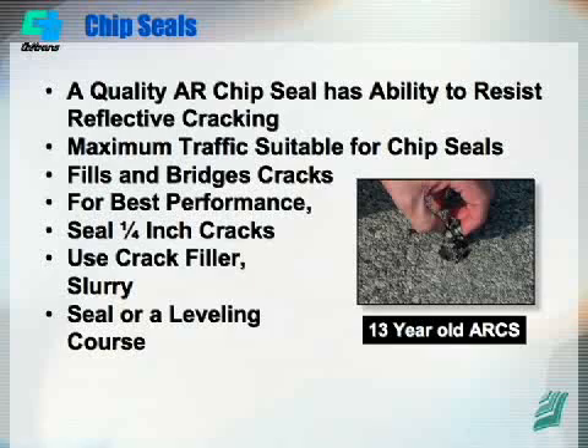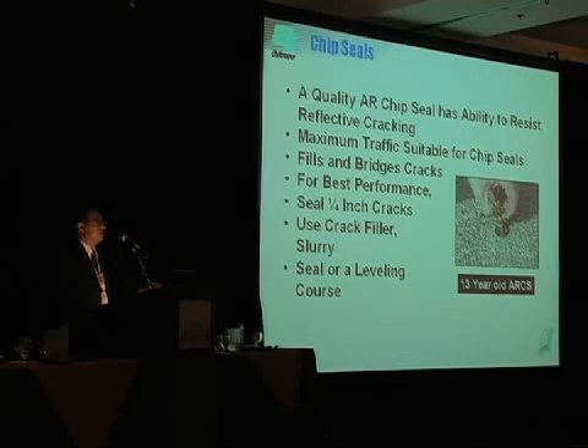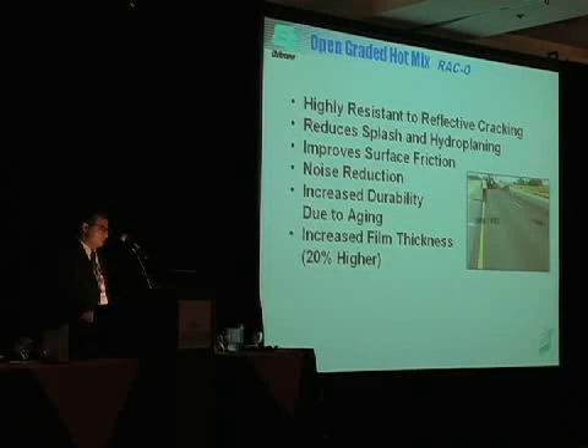Asphalt rubber resists reflective cracking, and it has been proven over and over again with many different types of tests and field performance that the reflective cracking ability for asphalt rubber chip seals in particular, and the other strategies, is tremendous. We have looked at many projects where the cracks don't reflect for many, many years. Rubberized asphalt concrete open-graded is also very resistant to reflective cracking. This is a very good material as a surface. In fact, it has provided us with confidence in using rubber statewide and pushing this strategy to be utilized more and more.